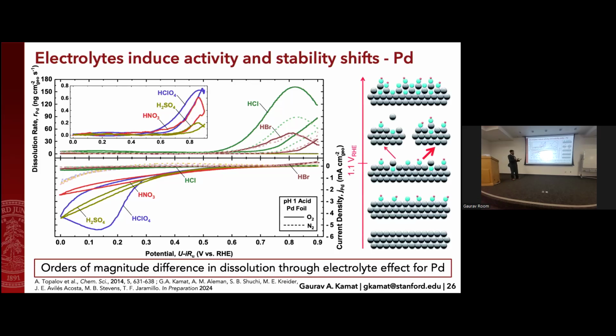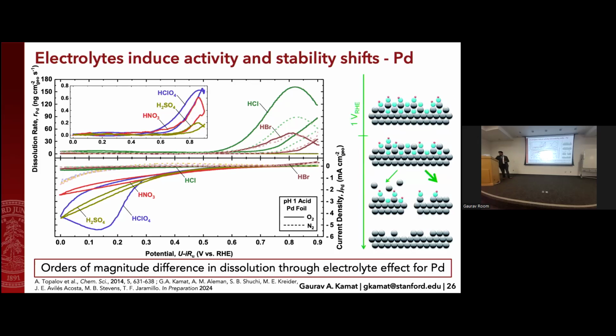And the mechanism for why this happens is actually very similar to platinum, and this is taken from a paper that studied platinum. So as you increase your potential, you're going to have oxygen adsorbates on your surface that will roughen the surface over time. And that leads to a little bit of initial dissolution on the upward potential sweep. And then as you sweep back down, that roughened surface is going to dissolve a little bit faster compared to your smooth surface. And so on your way down, you're going to have this large bump in dissolution that happens.